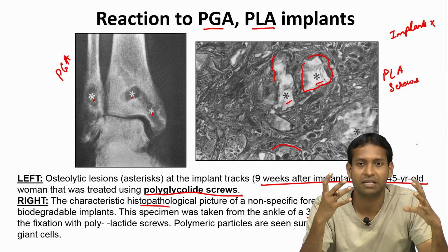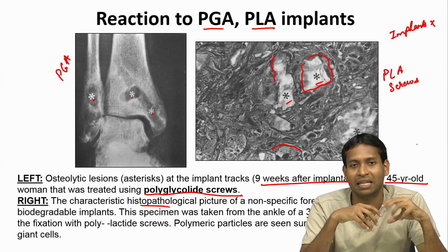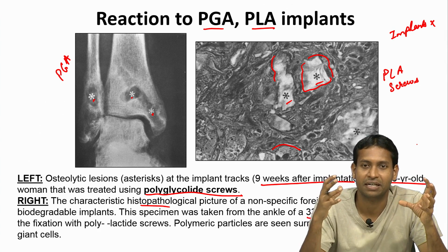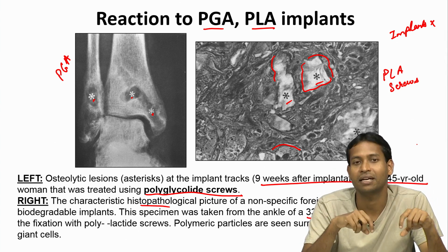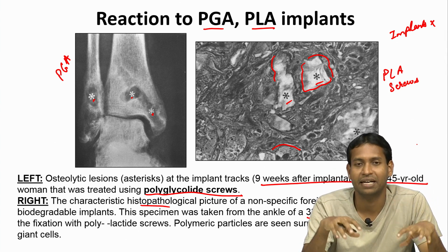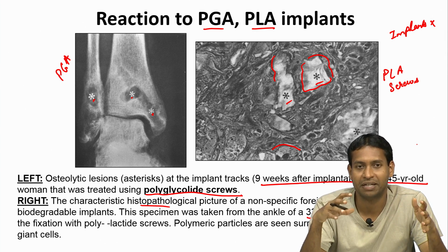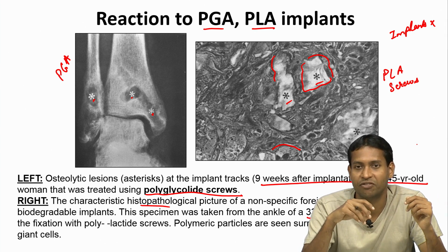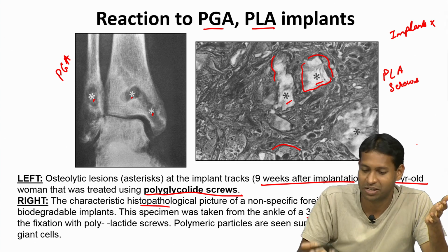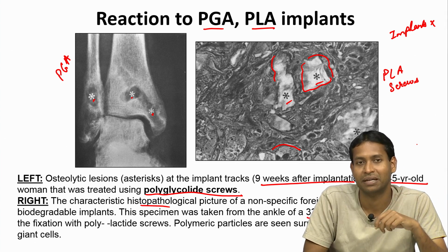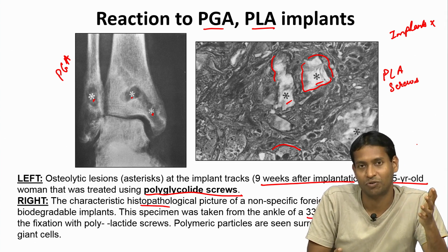But these big implants, when you put those in, they have problems, because now you have a lot of surface area for a given site, and these will degrade, these will create a local pH that is much lower than the physiological pH of 7, and it may cause inflammation, and outcomes like these might be achieved, which is not what you want.